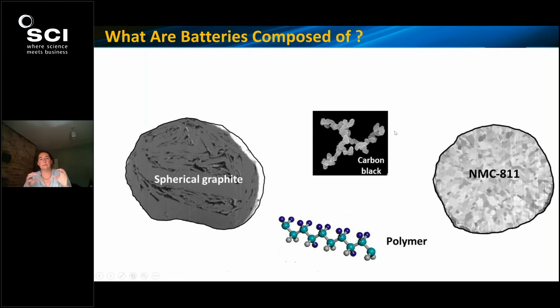Both anode and cathode active materials need to be very conductive. Obviously graphite is, but they still need higher surface area carbon additives to make sure that the bulk of the electrode coating can convey electrons in X, Y, Z directions. And they all need to be held together by a sticky polymer film. In the case of this one that you can see in the center bottom, this is a polymer called PVDF, or polyvinylidene difluoride, which has been, I think it's fair to say, a bit of a workhorse polymer since the initial manufacture of these batteries.